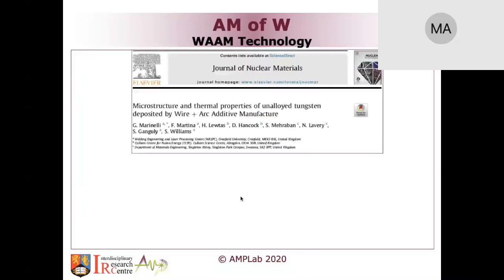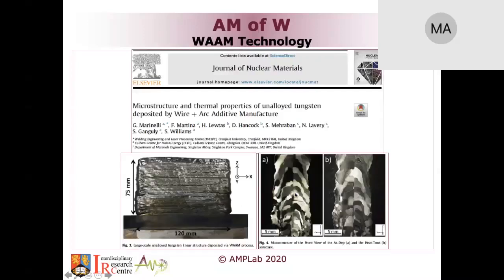Now, in parallel to laser powder bed fusion, there are other groups that looked into the wire and arc additive manufacturing process. In this case, they use a wire of tungsten and a welding technique to create a pure tungsten wall, as you can see. Yes, you can deposit tungsten and create a shape, but if you have good eyesight, you might be able to see a nice, lovely crack extending across the wall. Again, it's the same problem. You're likely to get cracks, you're likely to get anisotropy, you're likely to get all sorts of potential problems.